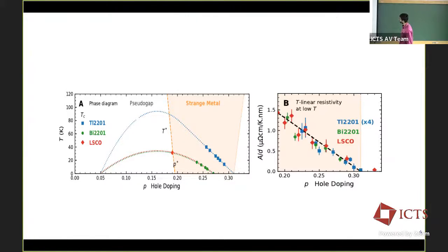Unfortunately, you probably do not see some color shading here, so let me just walk you through. This is precisely the schematic phase diagram that I showed you on previous slides. The y-axis is temperature, the x-axis is hole doping. This p-star is exactly what I showed you before, that there is some phase transition between the low doping and high doping phase. What is shown here is this shaded region. It was presumed that this strange metal basically emerges from this p-star point and that's it. It's like a fan-like structure.